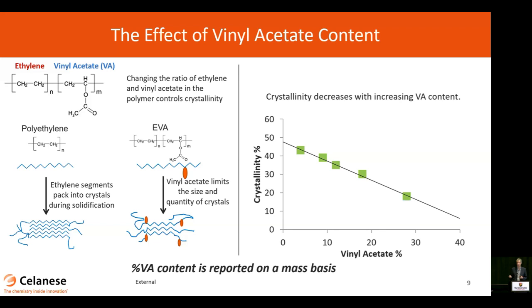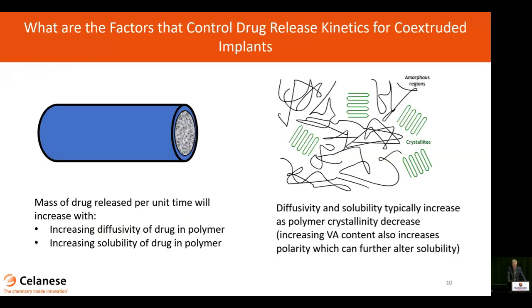By introducing vinyl acetate into the polymer backbone, the ester side group functions as sort of a bulky defect that disrupts and frustrates the crystallization and suppresses crystallinity of the material. So as you introduce more vinyl acetate into the polymer, you see the crystallinity will drop. If you made, say, a low-density polyethylene homopolymer, you might nominally get a crystallinity of 50%. But as you increase vinyl acetate, that drops down to eventually 0 until you make an amorphous polymer. And this is going to be very, very important for understanding release kinetics of an implant such as this device.